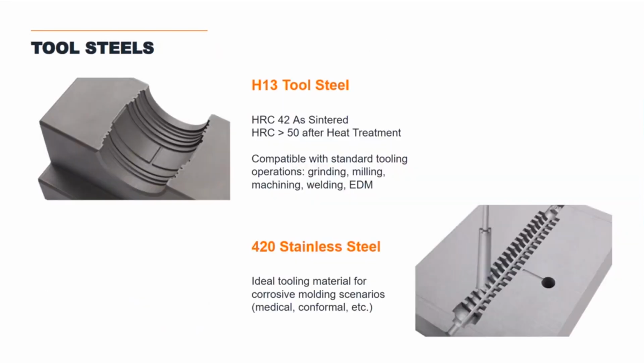The materials available: H13 tool steel, very common, durable workhorse material coming out of our process at a 42 HRC. It can be heat treated up to over 50 HRC, fully compatible with those traditional tooling operations as well, which I'll share after this. And then recently we just announced a 420 stainless steel. We announced this down at MPE. This is really an ideal material for corrosive molding environments and scenarios. Very, very common in the medical device industry, which is a lot of our customers, and we're really looking forward to this 420 stainless steel that you're seeing here as well.